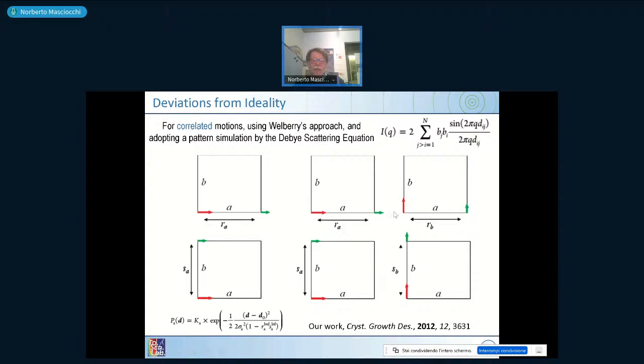So you have 4 parameters, and I have a 5th parameter, which is a correlation and a correlation angle between these two systems. So these kinds of movements define how much one atom reflects the movement of a neighboring one. So how much correlated are the movements in 2 dimensions. So it's possible to define a probability of a certain distance, which is not anymore a Gaussian system, which would be without this term, but these are the longitudinal and the vertical probability, which are defined in this paracrystalline method. So there is some mathematics behind, which was included into the Debye scattering equation.